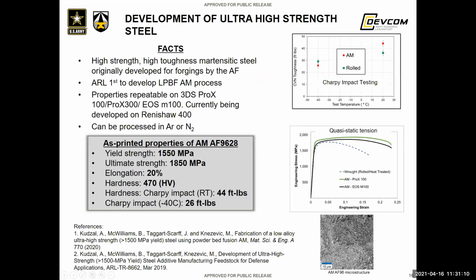And then going into the development, that was the development work for the ultra high strength steel. We were actually very successful with this. We were able to make one of the highest yield strength powder bed fusion steels. This was an Air Force steel out of Eglin Air Force Base, a variation of one of those steels but without tungsten, so it has a lot fewer issues, because tungsten steels are hard for recyclability.